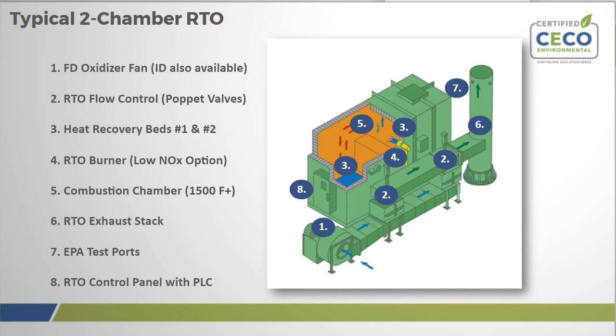But anyway, I want to reiterate, say you have ambient air coming into this thing, generally for a 95% efficient thermal oxidizer, the exhaust temperature will only be 30 to 50 degrees higher than the inlet temperature. So you may have 70 degrees going in and 120 degrees coming out. That shows you how thermally efficient these are when you have the combustion chamber in the middle of all of it at 1500 degrees. You're really recovering a large portion of that. And that's why they're the norm, and they're great.